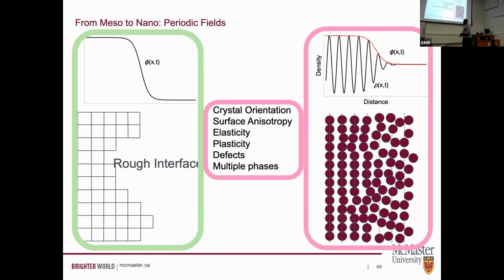But if we go back to somewhat of an atomistic representation, and I look at how from atom to atom these periodic structures are arranged, it turns out that I could get a lot of rich physics by treating my order parameter as a periodic field. Just as an example, if I'm treating my order parameter as a periodic field that has an equilibrium wavelength, if I happen to change that wavelength, Hooke's law tells me that it should come back. And so rather than describing my system by a uniform field, by using a periodic field I've inherently introduced elasticity, or at least zeroth or first order elasticity.